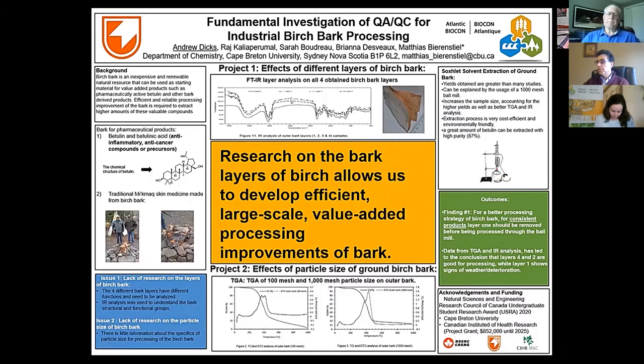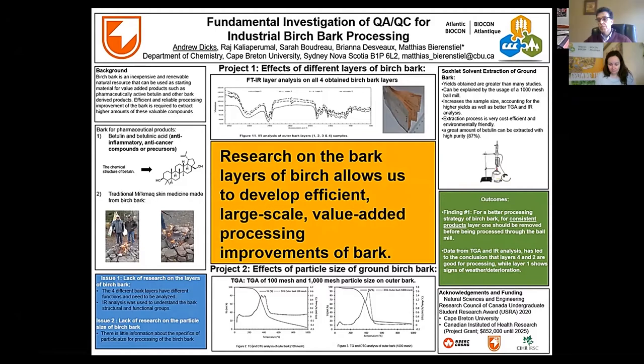So the first project was the effects of different layers of the birch bark. We used FTIR layer analysis, and it was performed on all four bark layers to confirm if there were differences that could affect the processing of the bark and the extraction of betulin. And what we found is that layer one has weathering and deterioration in some organic matter, and that causes processing to not work.